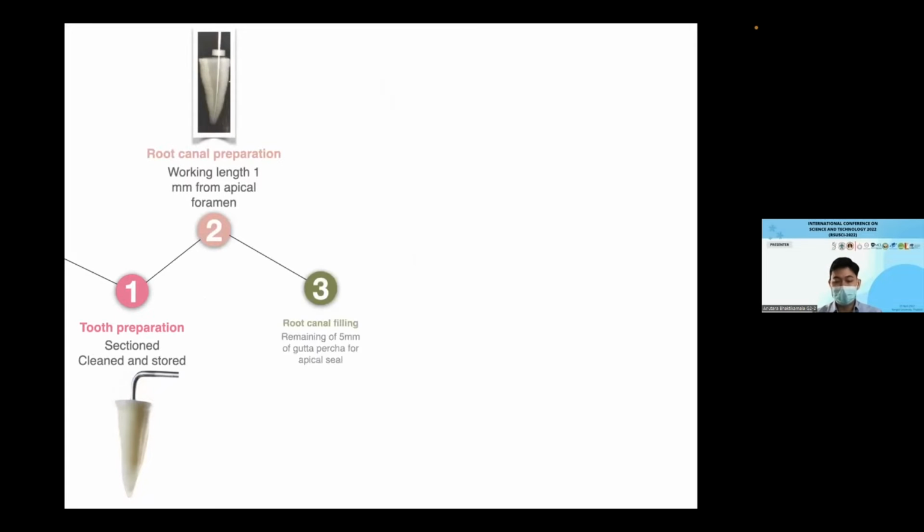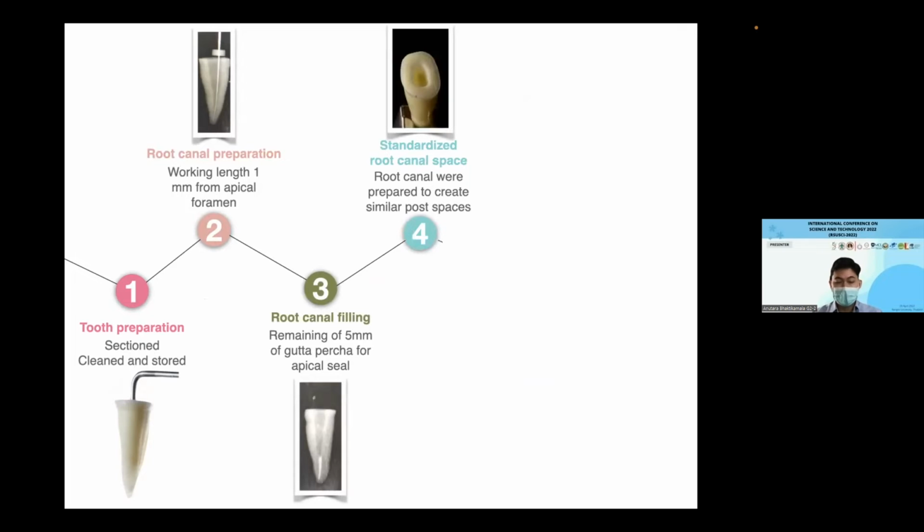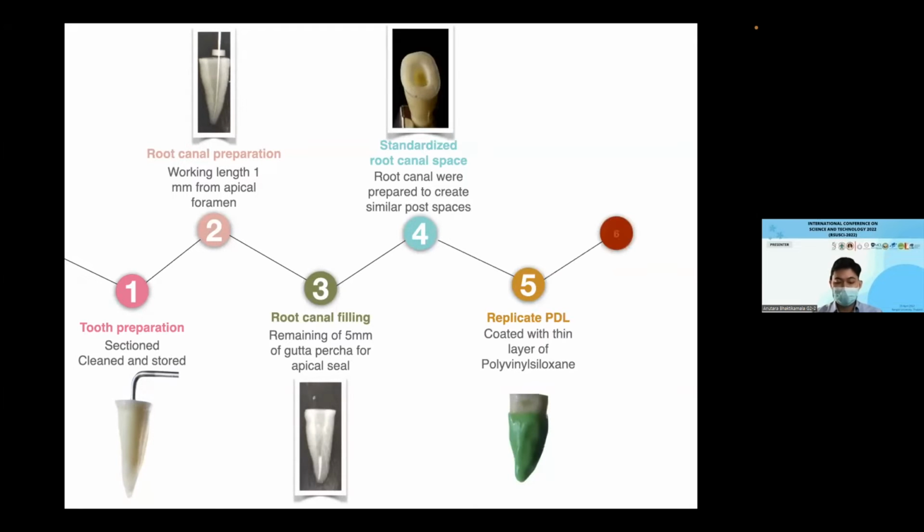For specimen preparation, the teeth were sectioned perpendicular to the tooth axis 2 millimeters above the buccal CEJ. After that, they received endodontic treatment and the post space was prepared, leaving 5 millimeters for apical seal. With the aid of a digital caliper and periapical films, a flared root canal with a standardized radicular dentine wall of 2 millimeters at cervical was created. Size 1 DT light post: the material was quartz fiber, double taper shape. Diameter is 1.5 at the cervical and 0.9 at the apical.